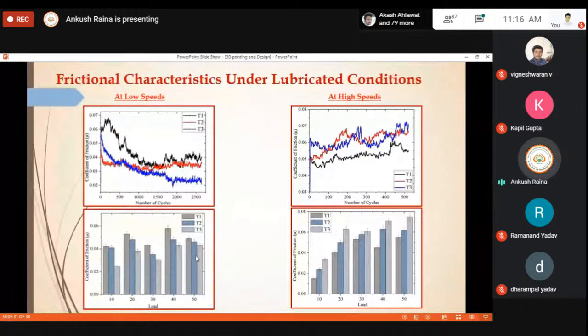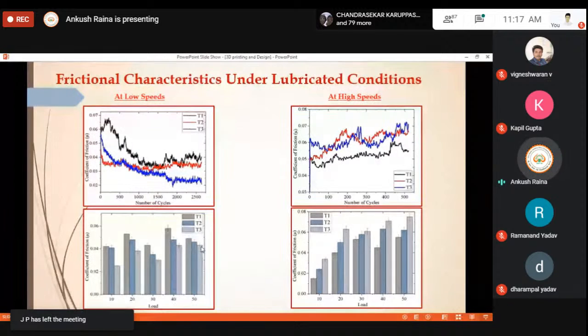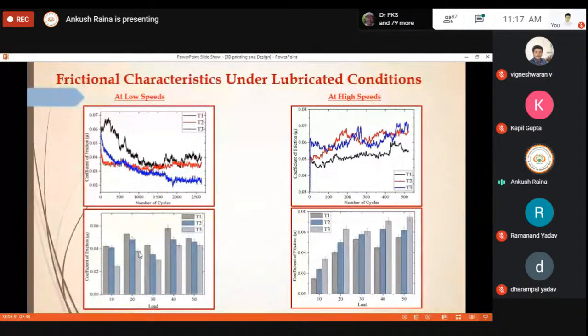Certainly, that is quite logical, because if you take into consideration the texture size of the T3 is more, and if the size of the texture is more, they have more oil retention capability. And if the oil will be more during the sliding operation, certainly the friction will be less. Which is quite justifiable in case of your low speeds, which is 100 rpm, which is very low speed. So that's why the T3 texture has shown minimum coefficient of friction in comparison to the other textures T1 and T2.